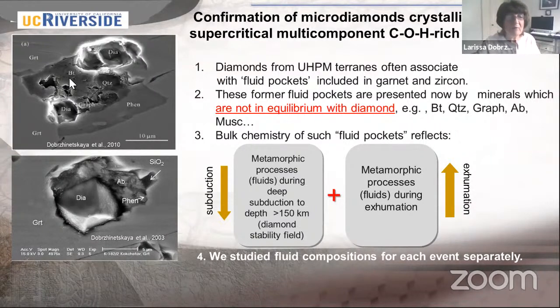So we understand now that these minerals are not in equilibrium with diamond: biotite, quartz, graphite. In this particular pocket inclusion, we have albite, diamond, phengite, and SiO2, which is now quartz. So we want to find the bulk chemistry of this inclusion, what this inclusion was before crystallization of these minerals. And we understand that there were two stages of this crystallization. First, ultra high pressure, where we had diamond, probably coesite, okay? That was probably during subduction to the diamond stability field.